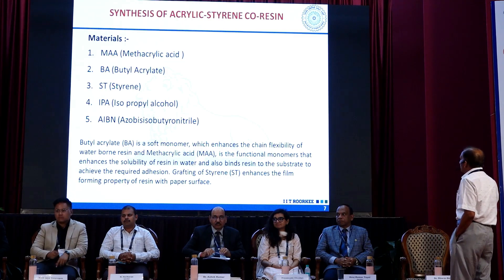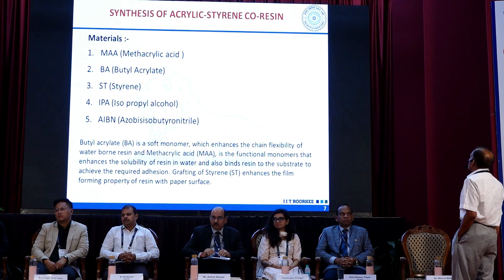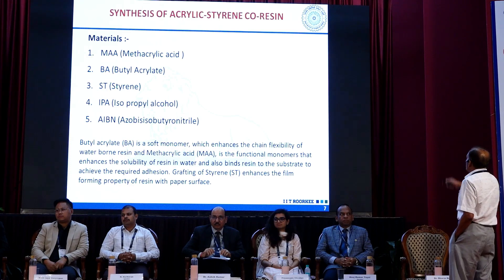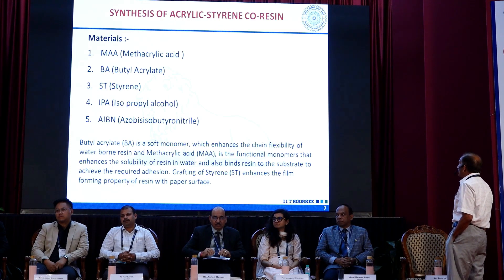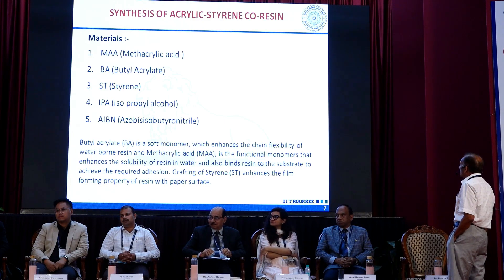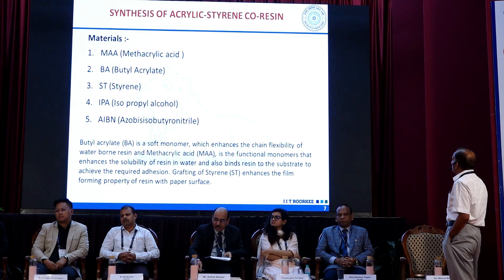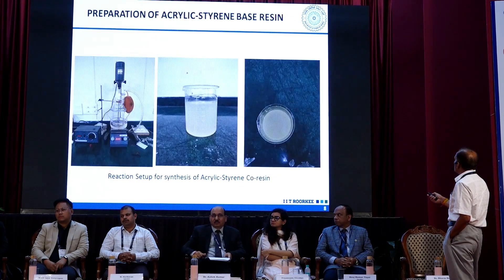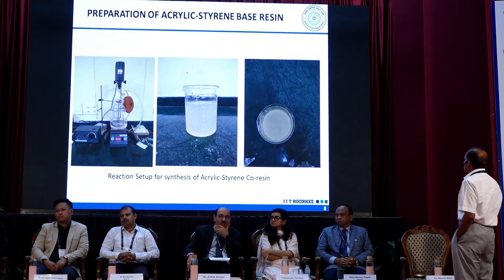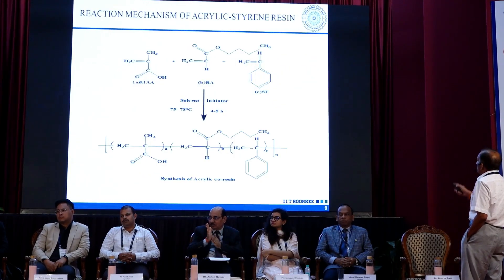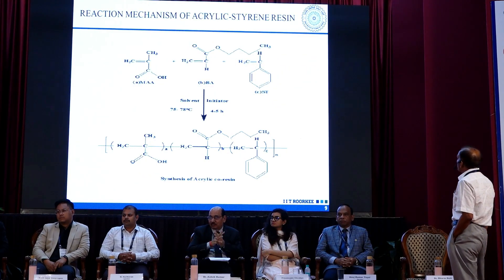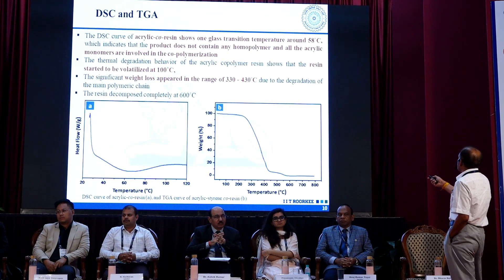We have used these chemicals during making this water-based coating: methacrylic acid, butyl acrylate, styrene, isopropyl alcohol, and azobisisobutyronitrile (AIBN). This is the reaction setup for the synthesis of acrylic-styrene copolymer, and these are the reactions taking place during the synthesis of acrylic styrene resin.